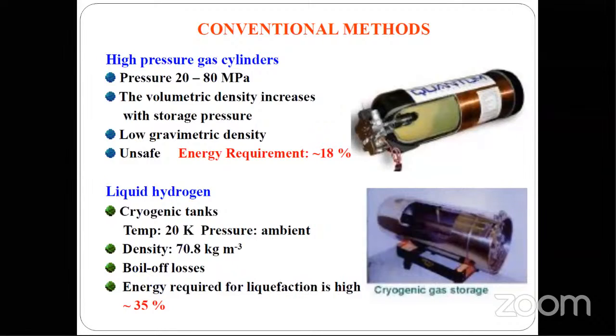But the problem here is that it is not safe to have an 800 bar or 700 bar cylinder with you in the vehicle. And one more disadvantage is that if you want to pressurize hydrogen to 300 bar, you have to spend around 18% of the hydrogen energy to compress it to 200 to 300 bar. So for compressing itself, you are losing 18% of the energy from the hydrogen. That is one of the main drawbacks of high pressure gas cylinders.